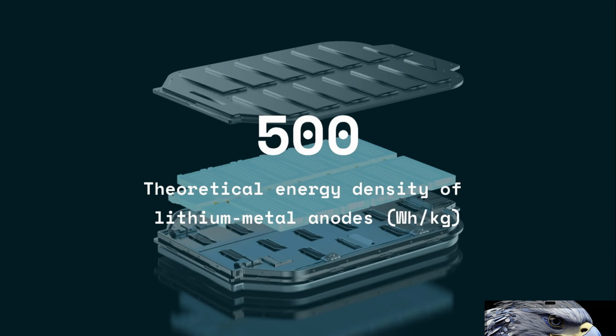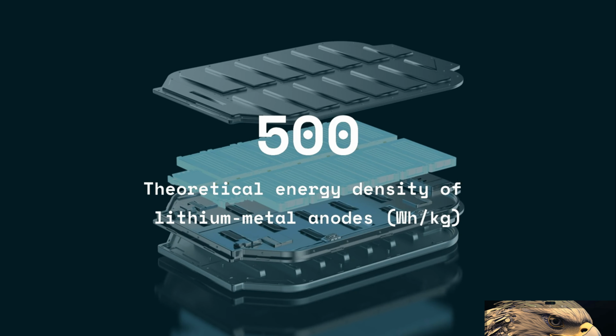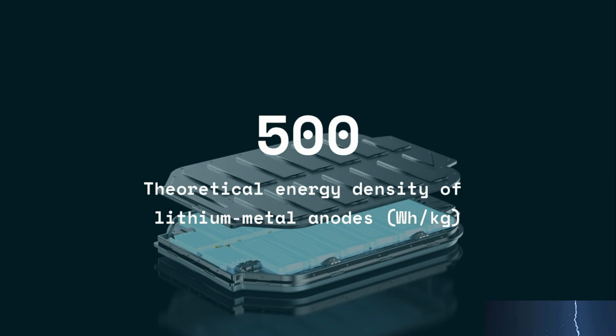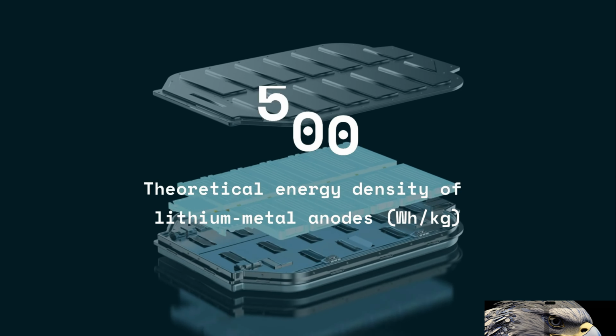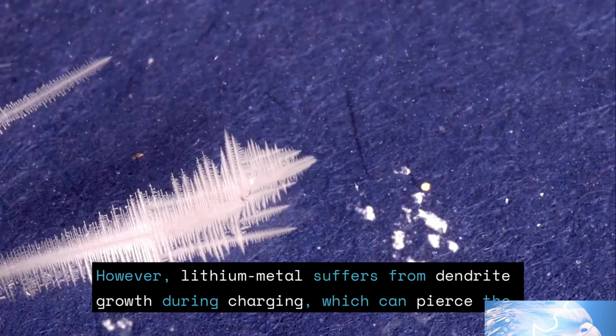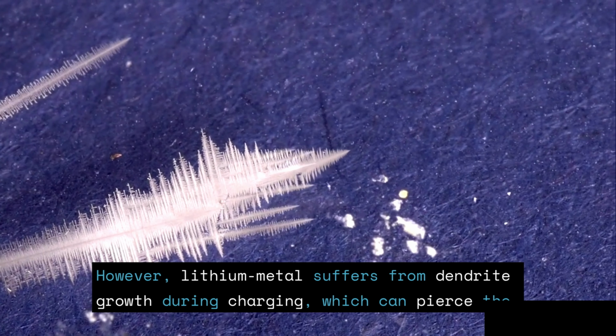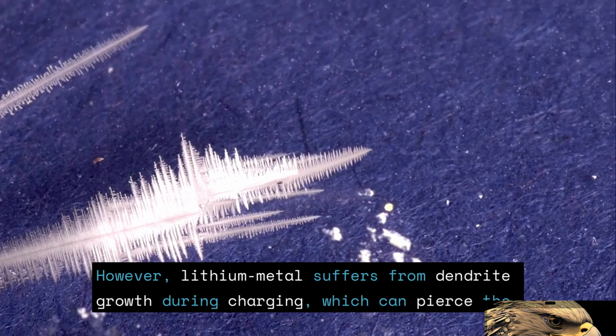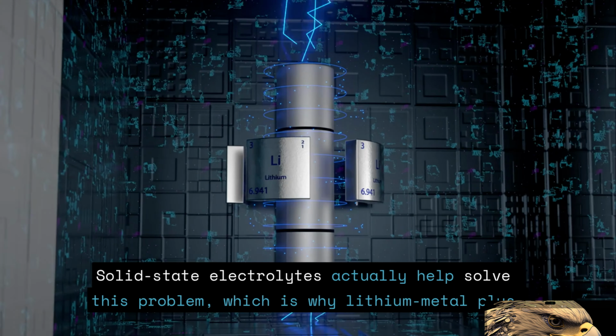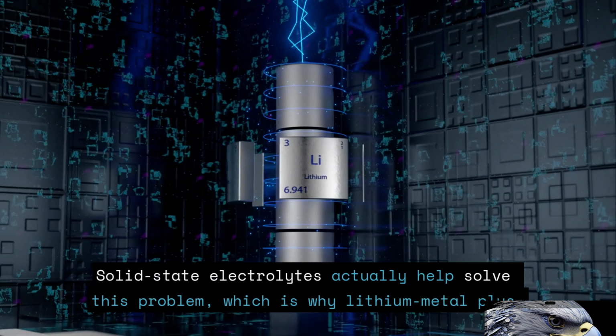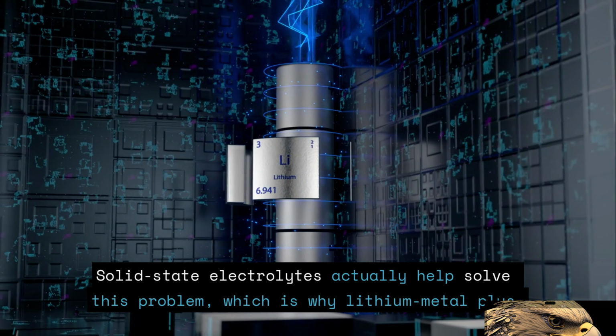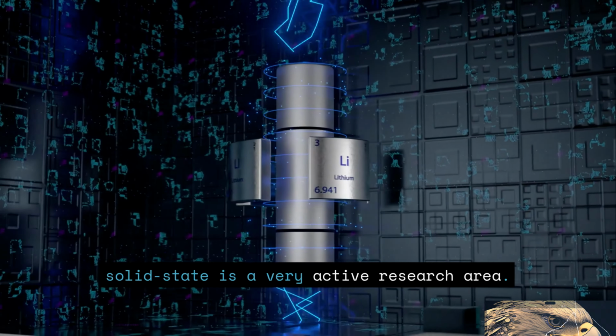Lithium metal anodes offer a theoretical energy density of over 500 watt-hours per kilogram, nearly double today's best Li-ion cells. However, lithium metal suffers from dendrite growth during charging, which can pierce the separator. Solid-state electrolytes actually help solve this problem, which is why lithium metal plus solid-state is a very active research area.